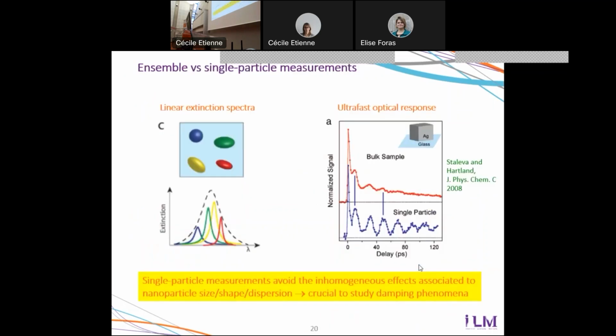Everything I presented up to now was experiments on a large number of nanoparticles at the same time, which was the configuration with which this type of experiment started. However, there can be a problem associated with this approach, which is that the signal corresponds to measurement over different nano-objects, which are never exactly the same. For instance, they have slightly different optical responses, vibrate at slightly different frequencies, and cool with slightly different time scales. So there is always an averaging process involved with such experiments.